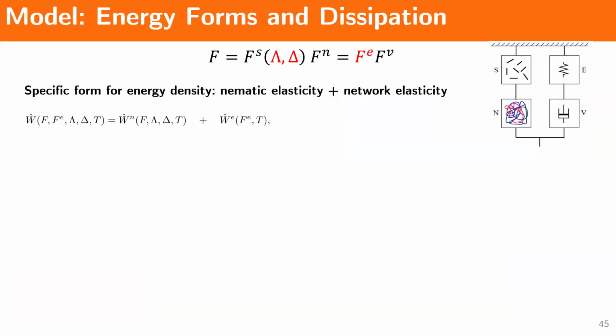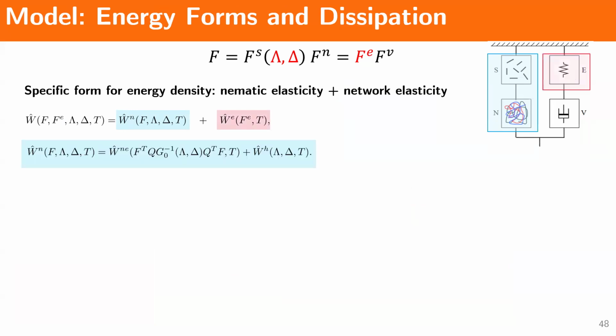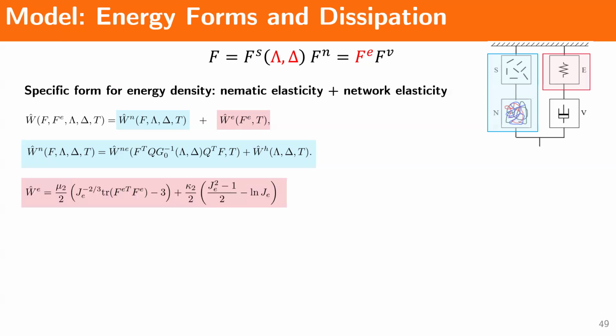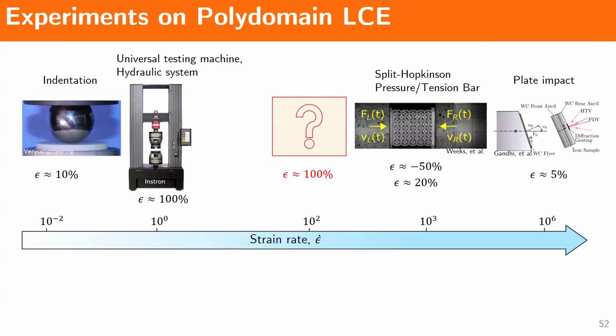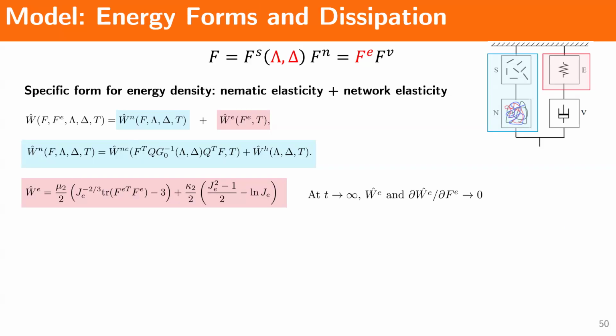Now we can specify a specific form for our energy density, where we have, again, the two energies. The first is the same energy as before, which is the equilibrium energy that we've seen earlier. This is exactly the same thing, where we have some elastic energy with respect to the spontaneous deformation state, or the energy-minimizing state. Then you can add to that the non-equilibrium energy, so to speak, of this elastic response of the rubber, and we just assume a very simple neo-Hookean form of this energy. We have to ensure for this energy that at time infinity, or at true equilibrium, the term from this energy goes to zero, and the stress associated with this additional energy also goes to zero.